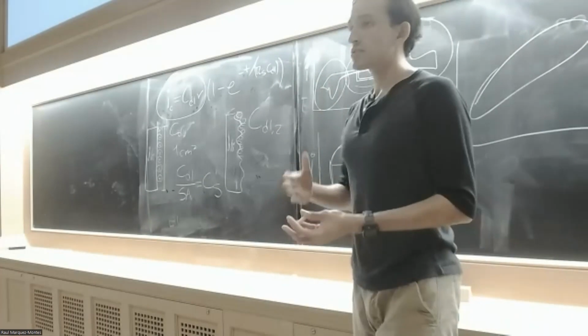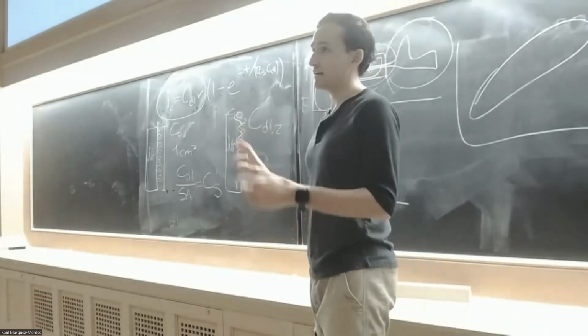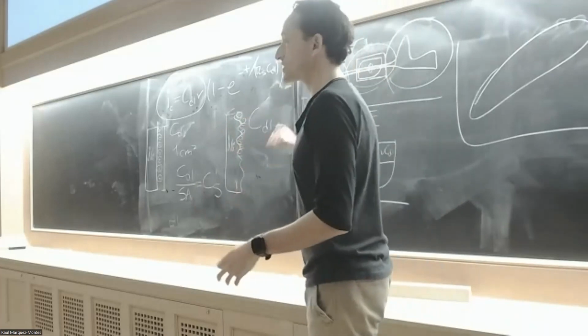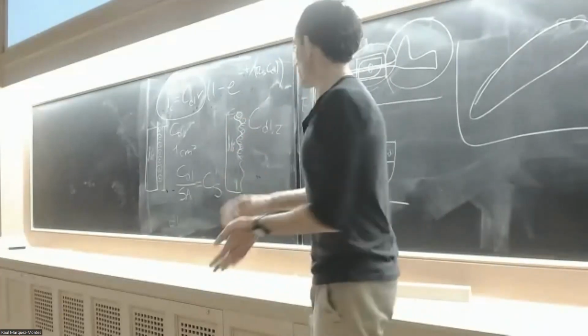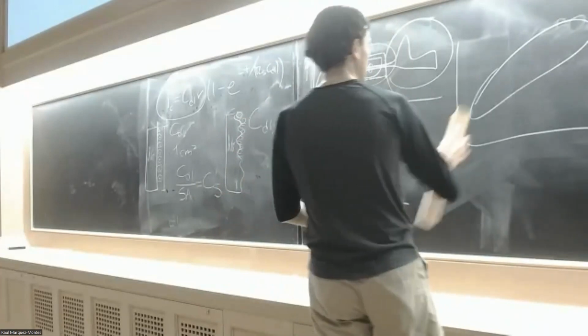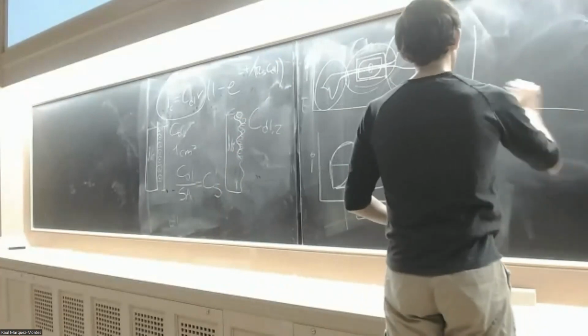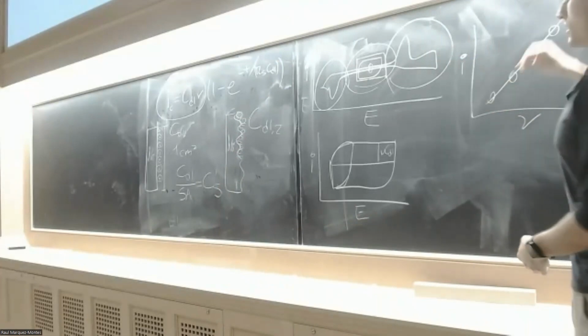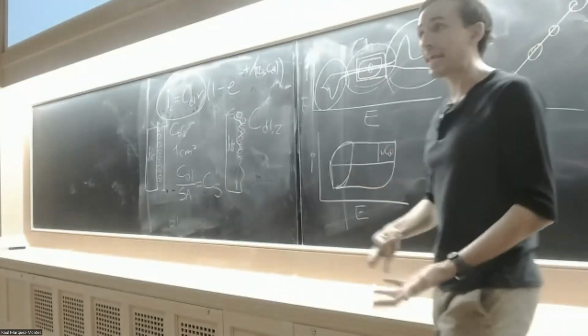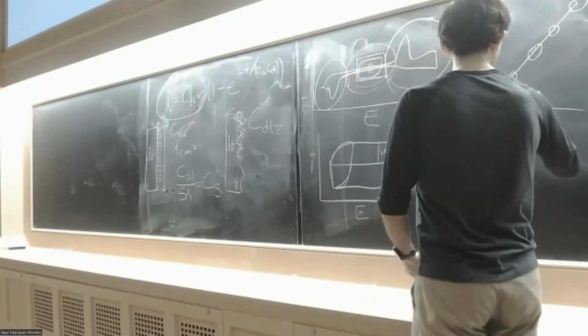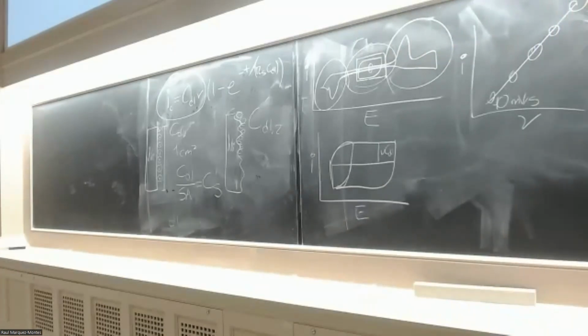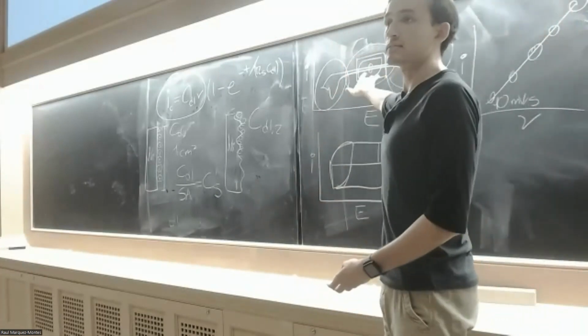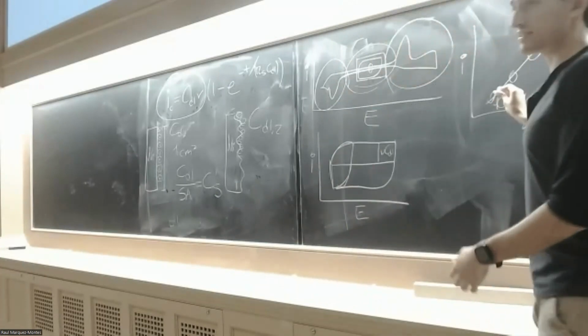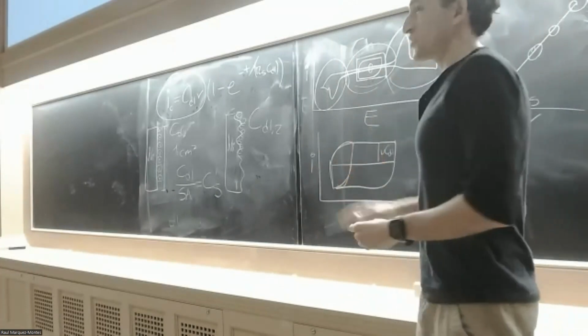Fourth consideration, we're changing the scan rate. Because this is a capacitor, a non-ideal capacitor, we should be able to replicate this process at any scan rate. So you should try scanning different values. If you have this plot here, current and scan rate, the more points you have, the better. Because you can say, okay, this material behaves like a capacitor from 10 millivolts per second up to 1 volt per second. If this is true, that means that your material truly behaves as a capacitor on this section of the curve. Sometimes you will see that this behavior only happens at a very small scan rate. And sometimes some people argue that's not reliable.